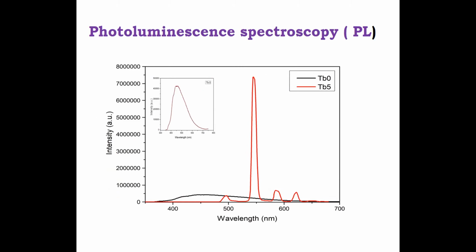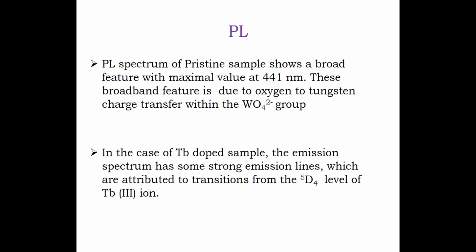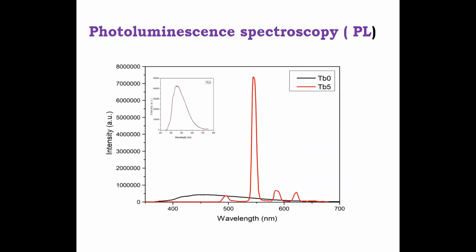Then next is photoluminescence studies. The PL spectra of both the samples are shown here. The PL spectra of terbium-0 is shown in black line, and the terbium-5 is in red color. And the PL intensity of terbium-0 is very less as compared to the terbium-5.